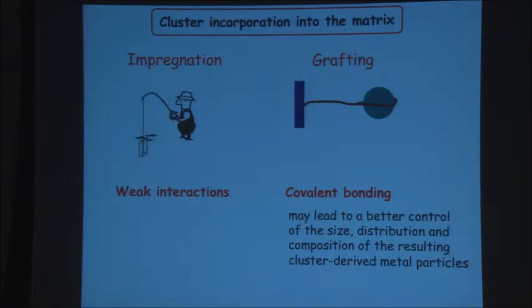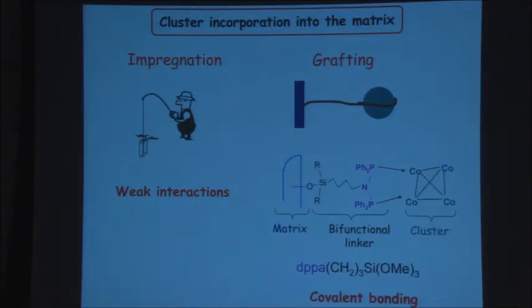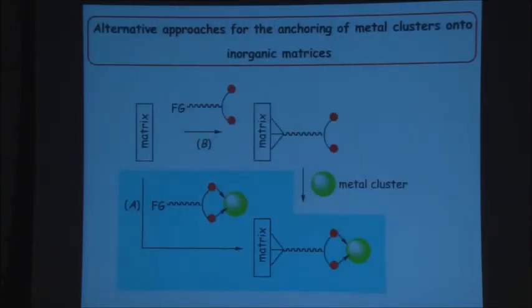Impregnation is a way we classically do, like when you prepare column chromatography. But if you want to have a stronger interaction of the cluster with the support, you can think of a grafting mechanism. And then by covalent attachment of the cluster to the support, you may have a better control of the loading of the cluster and the dispersion of the cluster into the support. So we use different approaches, and here is typically an example of a linker we use to attach the cobalt-4 cluster to the support with the OH groups by having this diphosphine functionalized here to nitrogen to an alkoxysilyl group. So this bifunctional linker is a kind of a hybrid ligand. Two sides contain the phosphorus, the other one contains the silicon that will be attached to the surface. And that will allow you to make a covalent attachment, if you wish, to the cluster.